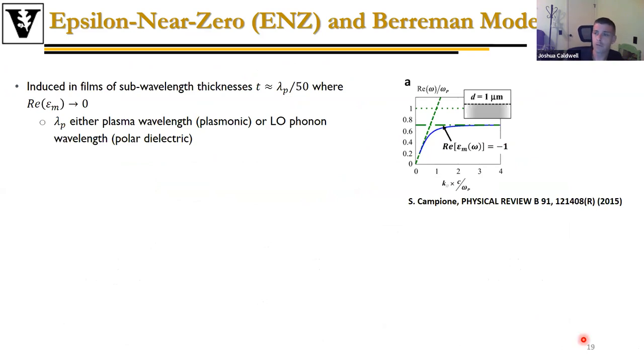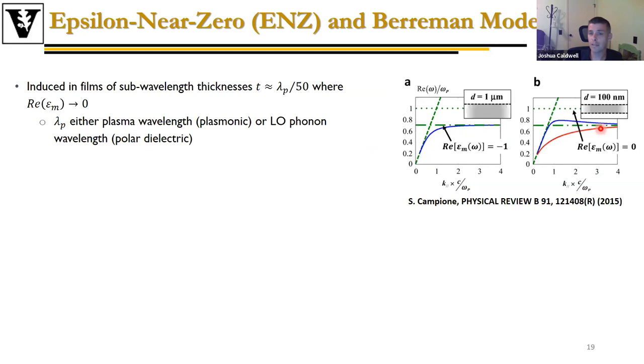But to do this, we want to use nominally flat films. And so one of the things we needed to look at was how can we actually use a flat film for realizing thermal emission? And so in doing so, you can couple to what's called an epsilon near zero mode. So here's my surface plasmon polariton dispersion. This is from a paper from Campione, where you can see the traditional dispersion as we approach within a thick slab. However, if I start shifting towards a thin film, I can support polaritons on both the top and bottom interfaces. And when the evanescent fields inside that structure, inside the polaritonic medium, begin to overlap, you get a strong coupling between those two modes. This causes a splitting and results in two different branches. This upper branch is the one that we're going to be focusing on here, leading to this ENZ polariton effect.